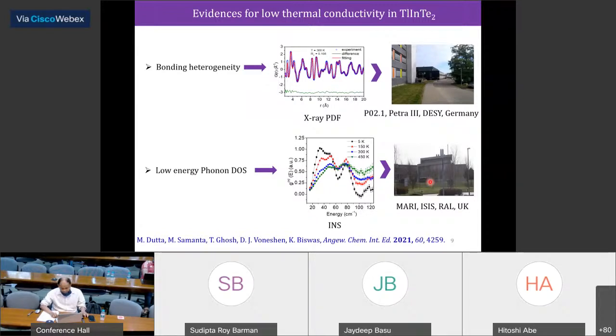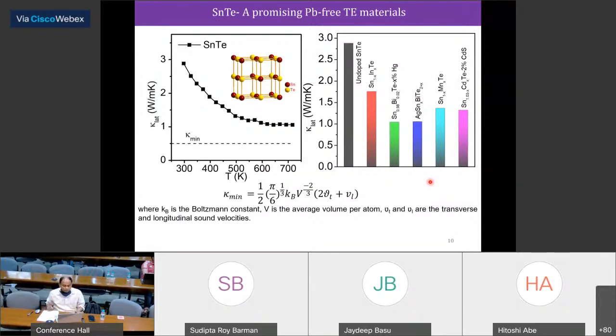Okay, sure. So the last part of the talk, I'm going to talk about tin telluride. Tin telluride is a well-known compound in solid state chemistry as well as in thermoelectrics, and it has a rock salt structure, sodium chloride structure, that means interpenetrating face-centered cubic structure. Its lattice thermal conductivity starts from 3 watts per meter Kelvin and goes down to 1.2 watts per meter Kelvin. But if someone calculates the minimum thermal conductivity from the sound velocity values as well as the volume of the crystal, the value is 0.5 watts per meter Kelvin. So when we started this work two to three years back, we thought, can we decrease the thermal conductivity of tin telluride to this much?